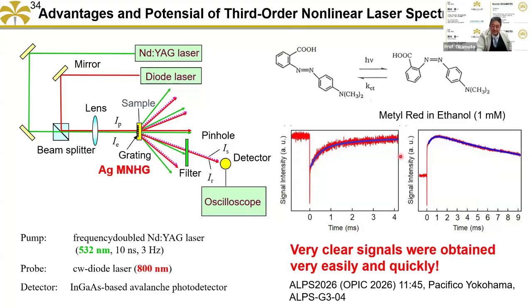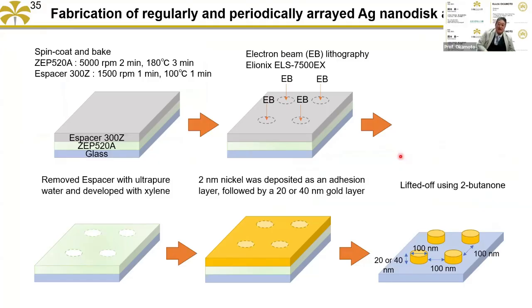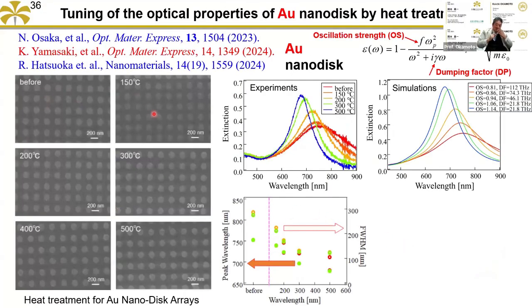That's another application. Before that, I used the random structure, but I also want to compare the regular structure. By using E-beam lithography and metal lift-off, we can fabricate a well-aligned structure of the same size. Surprisingly, we first thought that with the same size and good alignment the resonance peak would be very sharp and very strong, but it's not sharp and it's very broad. Then I added heat treatment after the fabrication of the structure. If so, the resonance peak becomes stronger and blue shifted. That's why the heat treatment is necessary for that structure, we found.